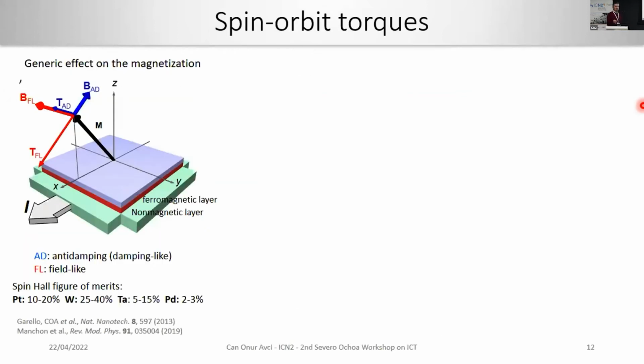So all these effects, and others that I did not mention, are collectively called spin orbit torques. And the spin orbit torques give rise to two types of torques on the magnetization when you inject a current. In the most simplistic case, you have a non-magnetic/ferromagnetic layer bilayer, and the passing charge current can apply large damping-like and field-like torques on the magnetization with the symmetry that I show you here.